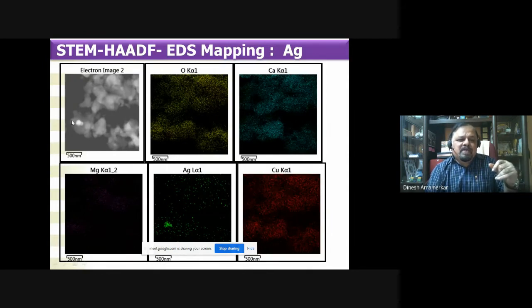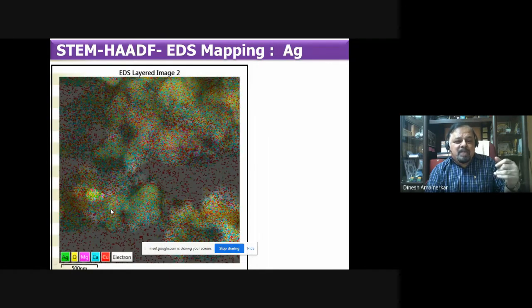Here also we can see, for example, where is silver here? This green color. We can see this is silver, this is silver, silver, silver, silver. Everywhere there is silver. There is oxygen. Everywhere there is oxygen here, like this. There's calcium everywhere, most of the places. Copper. Unfortunately, we have seen copper also at many places. Magnesium, a little bit reduced, and when you have taken the composite image, it looks like that.